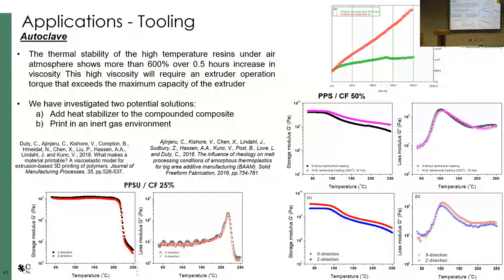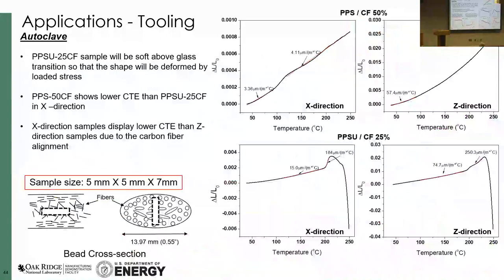This is why, because in injection molding, you are using a reciprocating screw. You are not in a dynamic process where your screw is already primed and always primed on there. What happened? Oxidation. It oxidized, basically. And then the viscosity shot up 600% over about half an hour, which overtorqued the motor and it became one piece. We have to take it off, burn it off, and go back. So this shows that even for material development, we went to a company that we are working with, we did heat stabilizers, and for some time till we get a new compound, we printed in an inert gas environment. So we're purging gas. One other thing that we need to focus on as well, right?